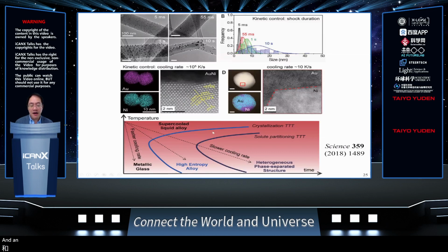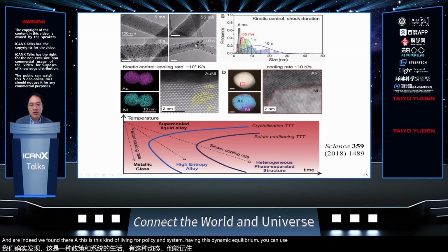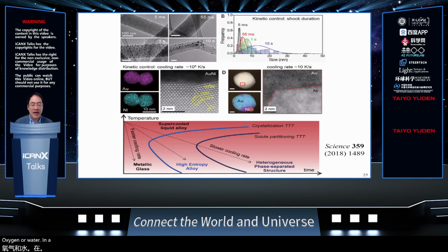And indeed, we found that with this kind of living catalysis system having this dynamic equilibrium, you can use it to control the particle size distribution to below 5 nanometers if you give it plenty of food to metabolize, and also if the cooling rate is appropriate. So we found that if you cool down very slowly, then this gold and nickel can have phase separation. And so they can have enough time to do the solute partitioning in this time-temperature transformation diagram. And later, if we expose this to oxygen or to water as an electrocatalyst, then this nickel can become nickel oxide or nickel hydroxide. So you would have a nanoparticle on oxide support catalyst.